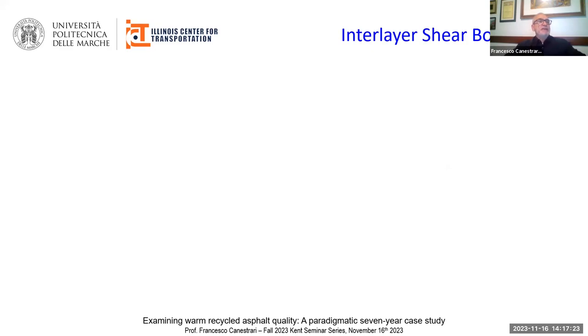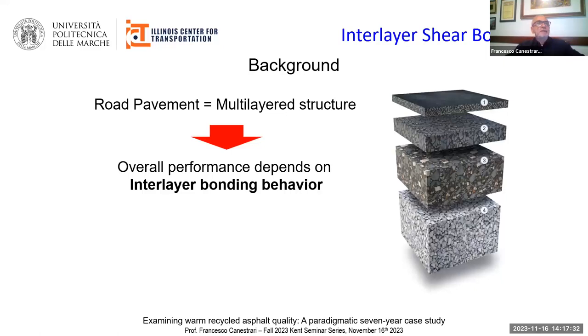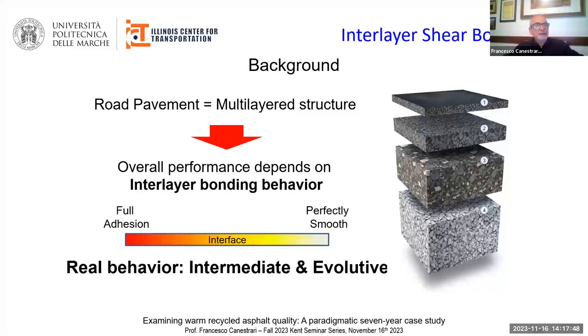Another fundamental aspect investigated in the 7-year case study was the interlayer shear bonding. It is well known that pavements are multi-layered structures and the overall performance under traffic loading highly depends on the interlayer bonding properties that can be modeled with two opposite conditions. On one side, we have the full adhesion response, and on the other side, there's the perfectly smooth response. Of course, the real behavior of interfaces is intermediate and evolutive under traffic loading. For this reason, the higher the interface shear strength, the better the pavement performance.